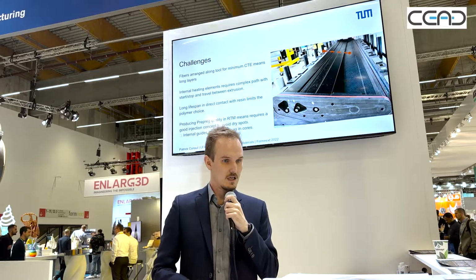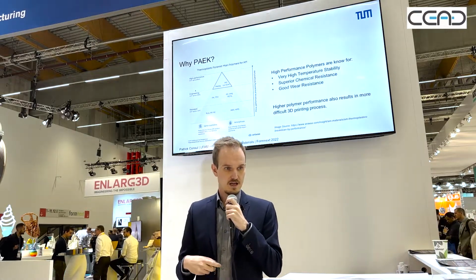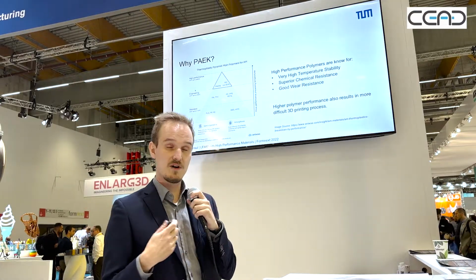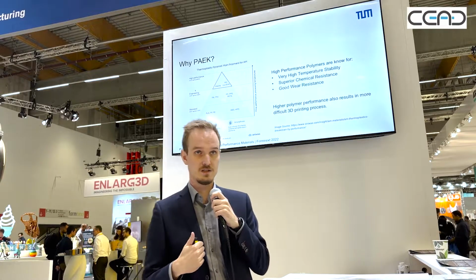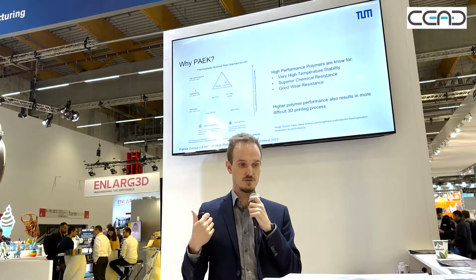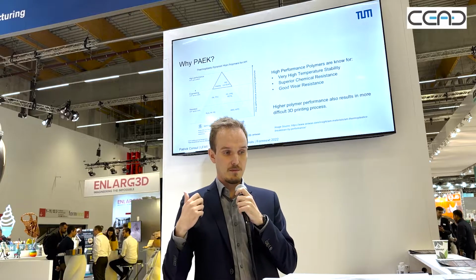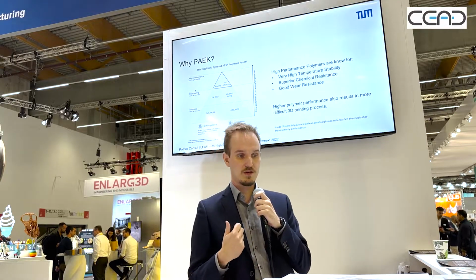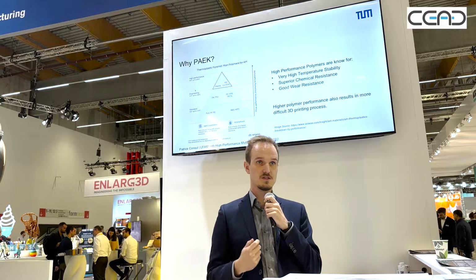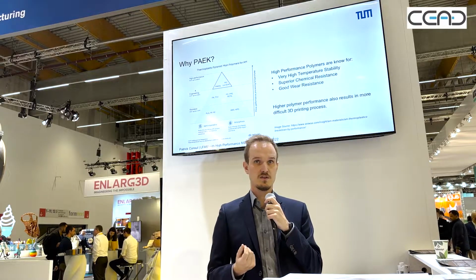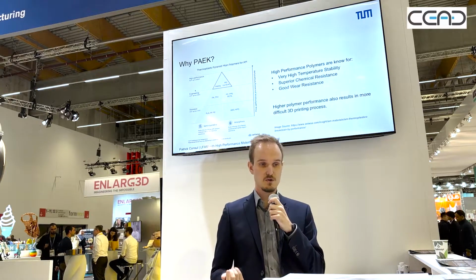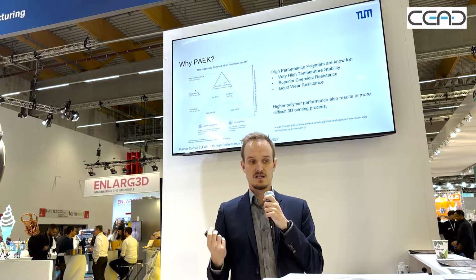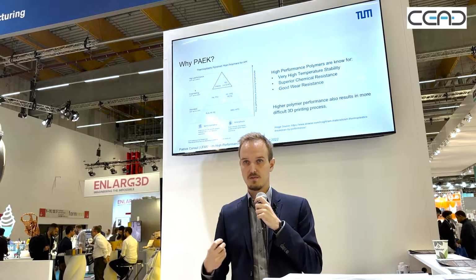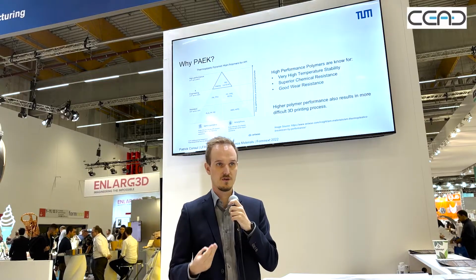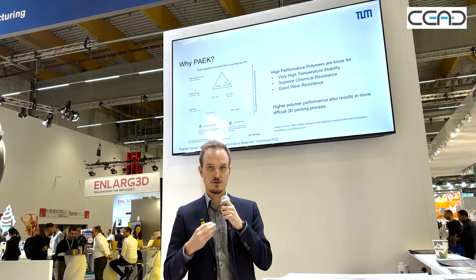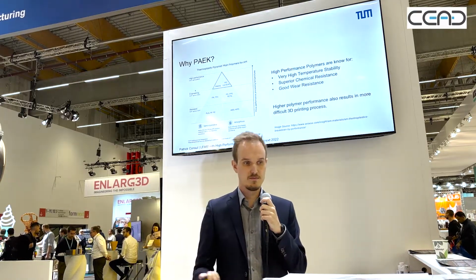Yeah. So why did we choose PAEK? Like I said before, we have high curing temperatures of 180 degrees, and PEEK is form stable until 240. And the most important two parts are the superior chemical resistance. Since it's semi-crystalline, it doesn't dissolve in the resin, it is resistant to most solvents, and it has a very good wear resistance. So if you demold your part quite often, you don't damage your tool surface as quick as you would with an amorphous polymer.